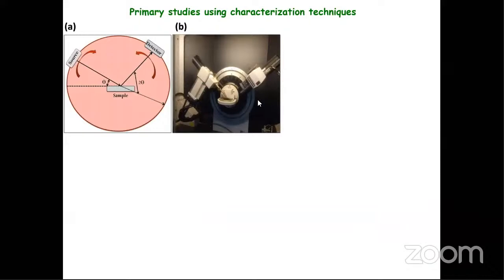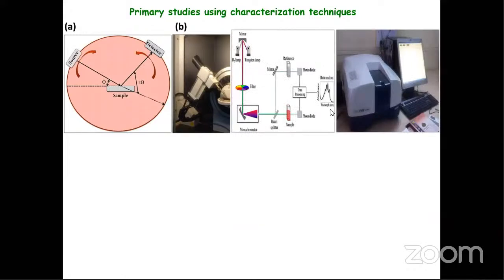Primarily, for characterization purposes, the X-ray diffraction technique is very useful to determine the crystallite size, because without X-ray diffraction we can't say whether this is a nanomaterial or a micro material, or which phase was formed in our developed material. This is the technique to determine phases also. What is the band gap of our developed material? UV-visible spectroscopy is also a very useful technique to determine the band gap.